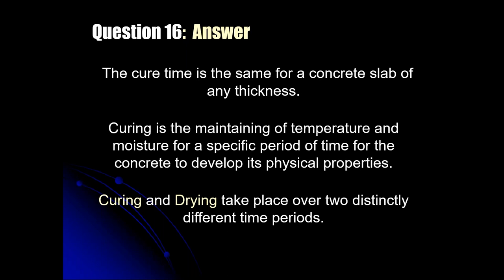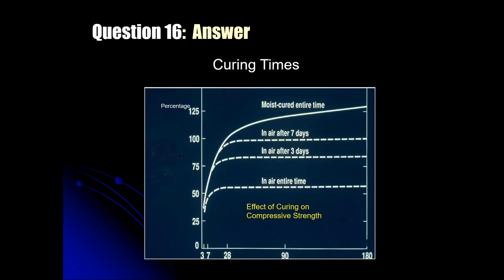Okay, because the definition of curing, or the operation of curing, is the maintenance of temperature and moisture in the slab for a specific period of time for the concrete to develop its ultimate, or its design, physical properties. So curing and drying take place over two distinctly different time periods. This was a study done at the Portland Cement Association years ago where they cast four different concrete slabs out in the backyard. The slab at the bottom, they just struck it off, bull floated, and left it. The second one from the bottom, the second chart line that you see, they cured it, kept it wet for 3 days, and then exposed it to the air. The third line, they kept it wet for 7 days and uncovered it and exposed it to the air. And the top solid line, they kept that slab moist cured, moist covered, if you will, for 180 days.